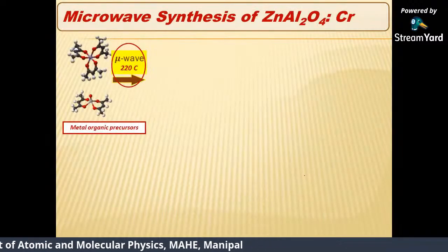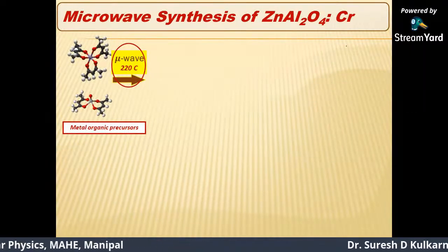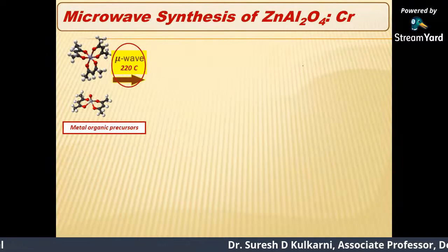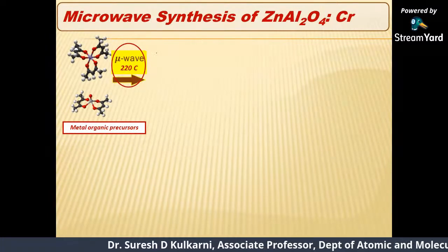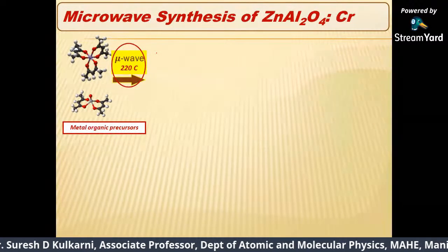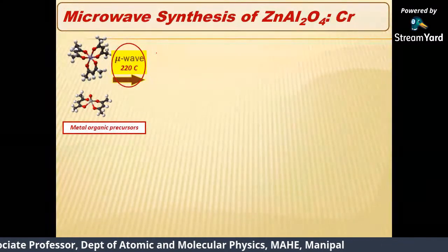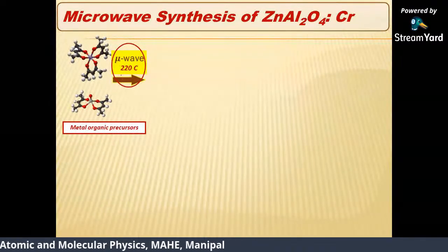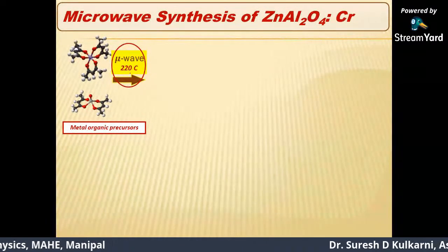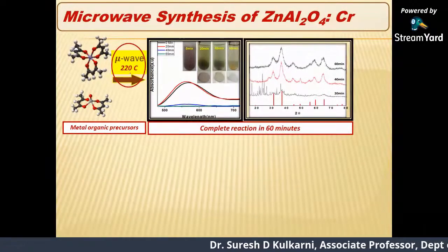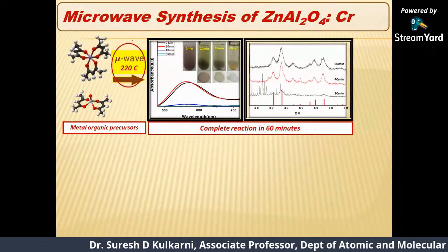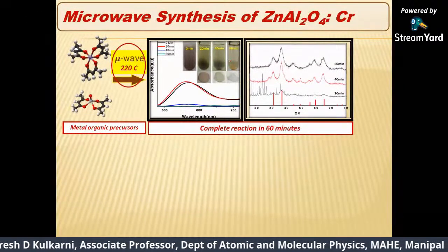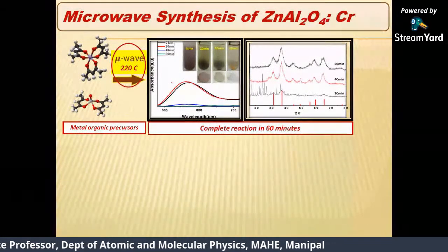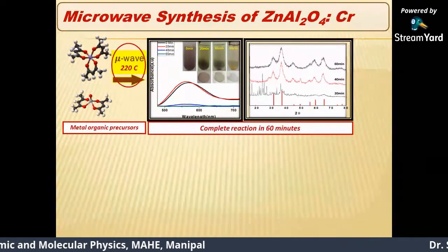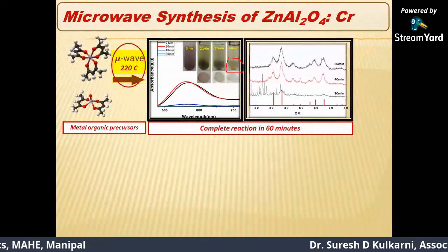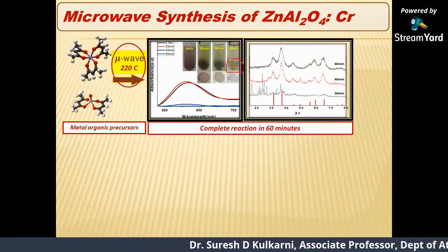Next, we try to dope chromium in the same material. In this case, because we have to use a chromium compound also, we have to change the synthesis conditions. Here the synthesis was accomplished at 220 degrees Celsius, and we had to optimize the minimum time required, and we identified that 60 minutes of time is sufficient. A simple absorption spectra tells me at 60 minutes all the chromium compound is turned into precipitate. Otherwise we had the green tinge of the chromium compound.